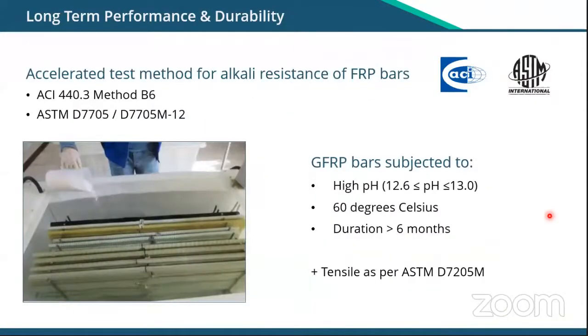The second aspect, as I mentioned, would be now environmental factor. So we are not looking at any kind of mechanical degradation. Now it's looking at chemical degradation. The main thing that could affect the performance of a GFRP bar is the alkali environment, so the high pH. And this is typically what you find in moist concrete. We know alkalinity is used in concrete. It's actually useful. It creates passivation and kind of protects the steel rebar. In the case of a GFRP rebar, alkalinity could or would degrade the GFRP bar performance over time.